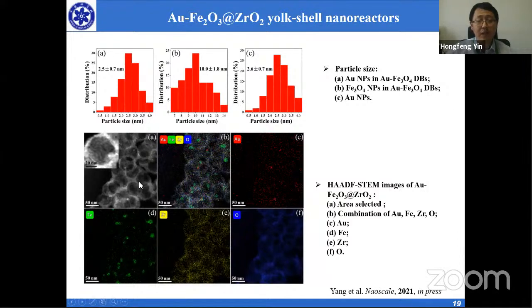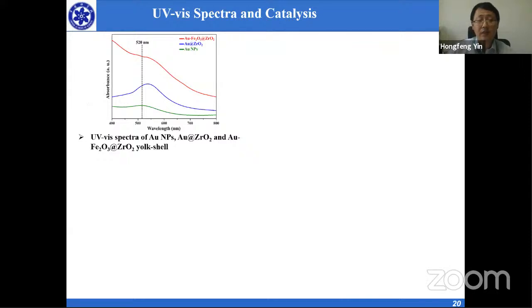For the mapping, we can see clearly the distribution of elements, and the distribution of gold and iron are at the same position. That means the gold and iron have pretty good contact with each other. And this is the UV-vis. We can still see that because of the interaction between gold and iron oxide, there is a red shift.